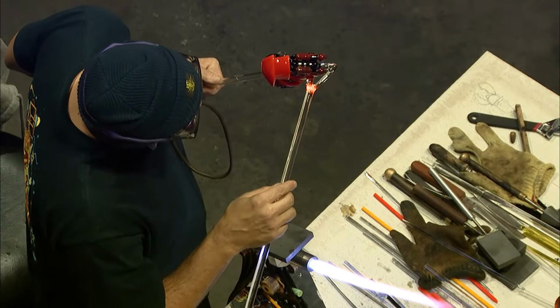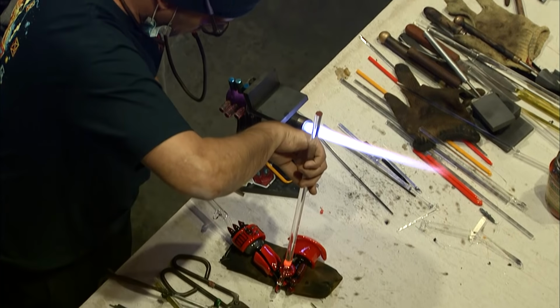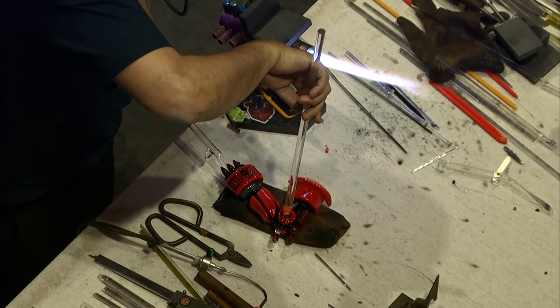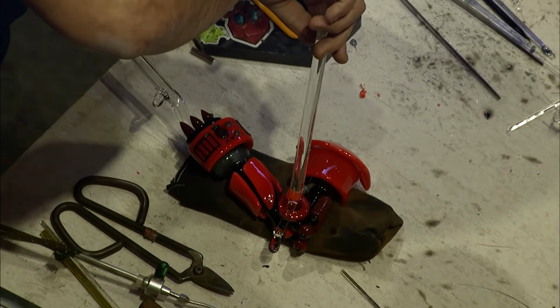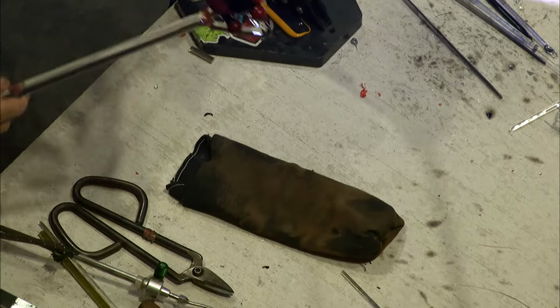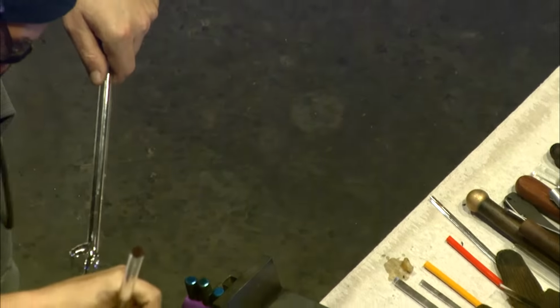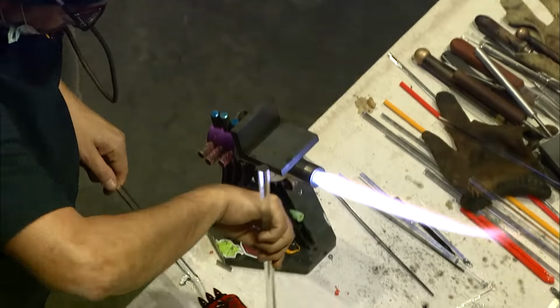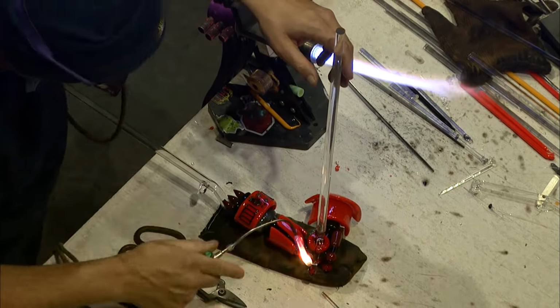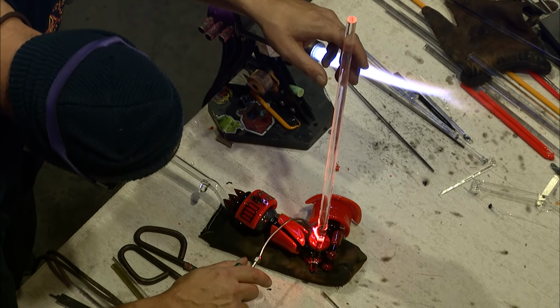Because borosilicate melts at a higher temperature, certain colorants that are used for lower temperature melting glasses tend to burn up at these higher temperatures, or they have different reactions with the boron oxide that goes into this glass. So in many cases, they had to discover new colorants or new combinations of colorants to get borosilicate glass into those same color families as what's available in other glasses. But at this point, the color companies provide us with so much in the palette. It is just amazing.